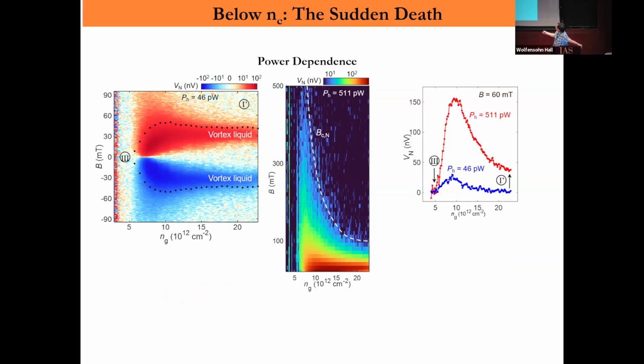First of all, there's no signal here at what I call the 1' regime. These two are maps that I already showed you. The only difference is that this map has a higher power of the temperature heater, which means a higher temperature gradient. You see this 1' happened at a density of about 20 at 60 millitesla. You have a huge signal when you have higher temperature gradient, but zero signal here. So we do not have signal in 1' only because the temperature gradient is small, our instrumental sensitivity is not enough to resolve it.